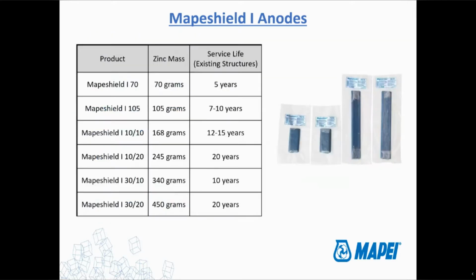But yeah, there's different sizes of anodes. 70 grams, 105 grams are pretty typical of what you see. There's some bigger ones too, you can see there as well. Basically, the more zinc you have, the longer it takes to consume all of that zinc. So if you want it to last a really long time, you use one of the really big ones. If you're just looking to maybe get a couple of years, you can use some of the smaller ones. And then, of course, there's everything in between available to you as well.